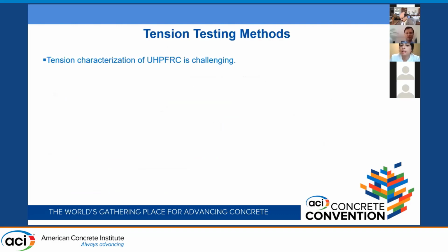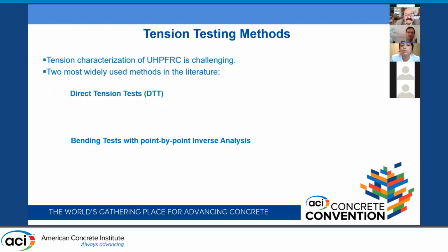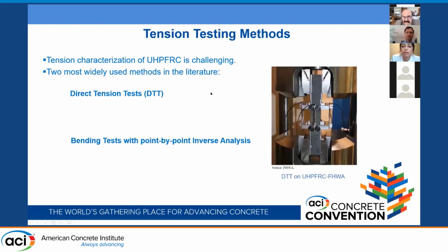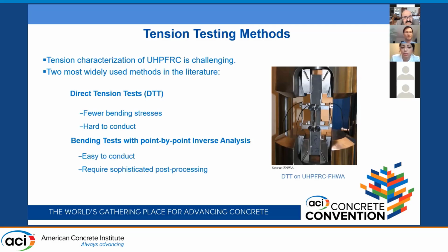Now, speaking about the tensile cracking strength, it's generally challenging to characterize the tension properties of fiber reinforced concrete and in particular UHPFRC. The two most widely used methods in the literature are the direct tension test and the bending test with a point-to-point inverse analysis. Here we can see a direct tension test. Direct tension tests generally impose fewer bending stresses on the specimen, but they are in turn hard to conduct. On the other hand, the bending tests are easy to conduct, but they require sophisticated post-processing to predict the uniaxial tensile behavior. So every method has its advantages and disadvantages.